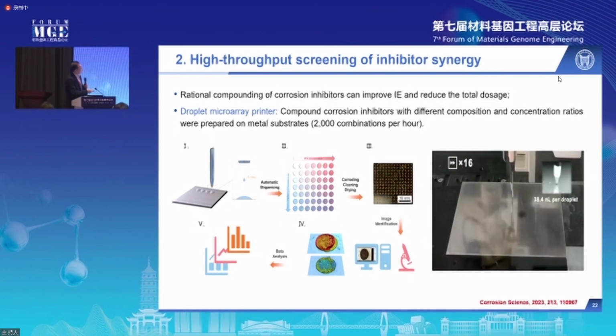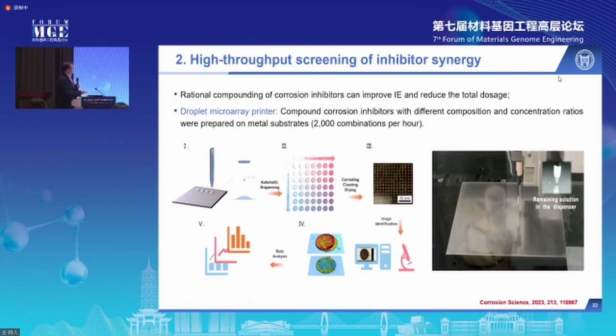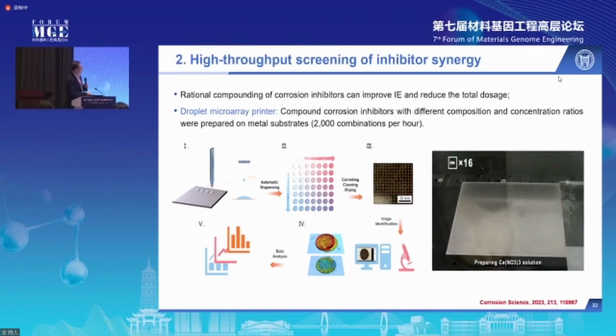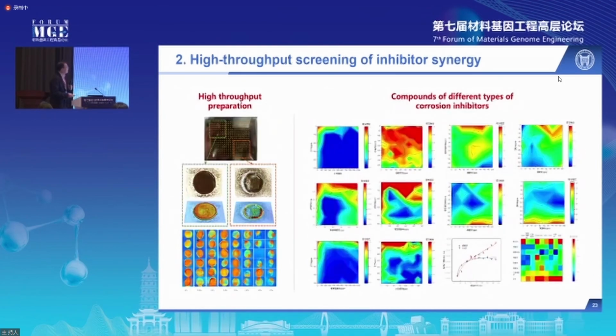And after letting it corrode for a while, we can analyze the surface morphology, the corrosion depths, or electrochemical signals to get an idea of the corrosion inhibition efficiency. And this is how it looks after corrosion. And after analyzing the surface conditions, we can very easily generate a heat map like this, showing the synergy of multiple corrosion inhibitors.